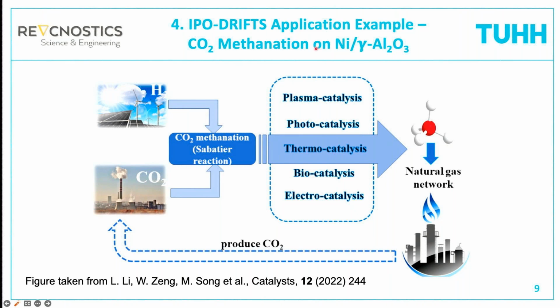This is CO2 methanation on a supported nickel catalyst. The nickel sits on a gamma alumina support. I already mentioned that this reaction is very important right now to battle climate change, because we can convert CO2 from a local source like a power plant with green hydrogen into methane, which is synthetic natural gas, and then this can be fed to the gas grid to close the carbon cycle. And you can do this in various ways. I'm going to show you the thermocatalytic way on such a nickel gamma alumina catalyst.